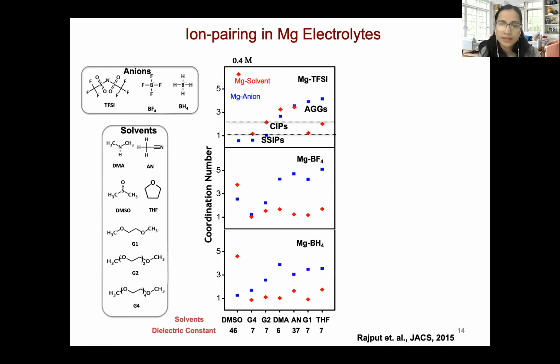So to further investigate this degree of ion pair formation, we prepared an electrolyte matrix with different anions and different solvent molecules. And we considered solvents with a range of dielectric constant, as well as some linear and cyclic geometries. Okay. And we looked at the coordination number of the cation and solvent and cation and anion to get an estimate of the solvation structure here. So for better solvation, you would want to have higher coordination number of magnesium and solvent and lower coordination number of magnesium and anion. And we learned that pretty much all of these magnesium salts have a very strong tendency to form either ion pairs or aggregates in the solution.